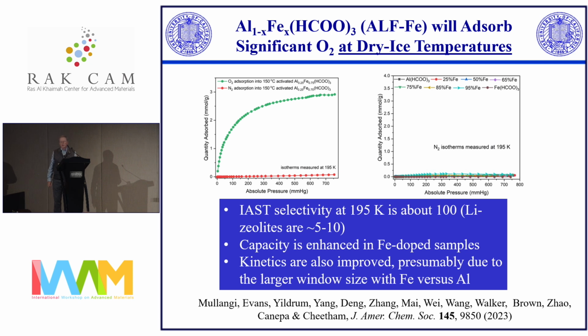So here's the separation. This is, on the left, the adsorption isotherm of oxygen into ALF, and down on the right-hand side, there's the nitrogen. So you see it doesn't adsorb, as I said. The oxygen goes in very well. It goes in at room temperature, but not as much as we would like, at 1 atmosphere. But then as you cool it down, it's optimal at about 200 K, and then it goes down again. So the selectivity is around about 100, so it's more than an order of magnitude better than the zeolites, and it absorbs the oxygen instead of the nitrogen.